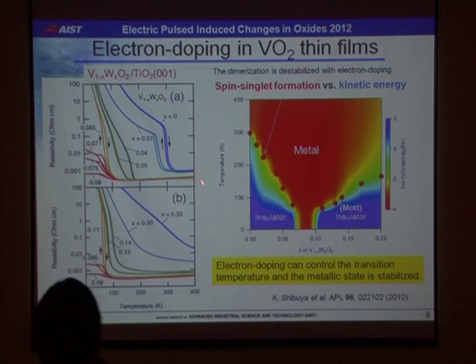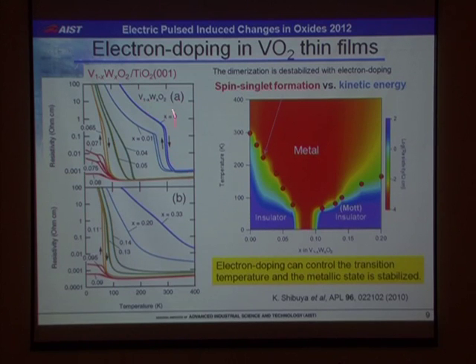As you can see, with increasing tungsten concentration, the transition temperature shifted monotonically to lower temperature. Eventually, a metallic ground state was observed between x equals 0.08 and 0.09. A further increase of tungsten concentration gives rise to another insulating state.